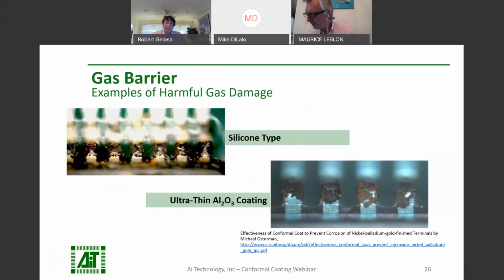Many industrial applications are sensitive to corrosion from these harmful gases. Here we see images of corrosion of electronics protected by a silicone-type conformal coating and an ultra-thin layer of coating. These were taken from a study on various coatings and their performance in an environment where corrosive gases were abundant. Silicone-type conformal coating was found to have the worst protection. Surprisingly, this ultra-thin coating was found to have the second worst among all the coatings tested.